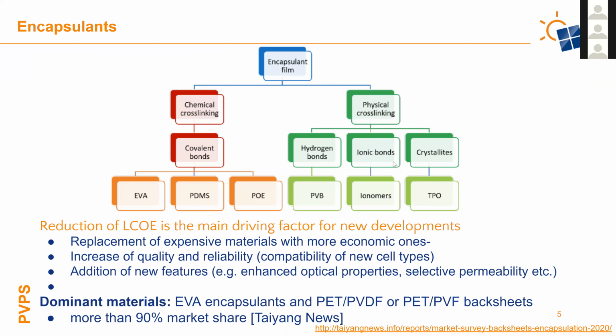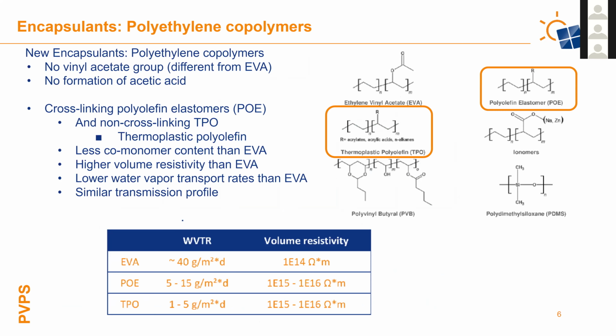So when we think of POE and TPO, these are polyethylene copolymers. There's no vinyl acetate group, so that's different than EVA, meaning you shouldn't get formation of acetic acid with these materials the way you do with EVA. Polyolefin is a cross-linking material, and TPO is a non-crosslinking material. TPO generally has a higher melt temperature than POE, but you can have shorter lamination times. Generally, they have higher volume resistivity than EVA and lower water vapor transport rates than EVA, though they generally have similar optical transmission profiles.